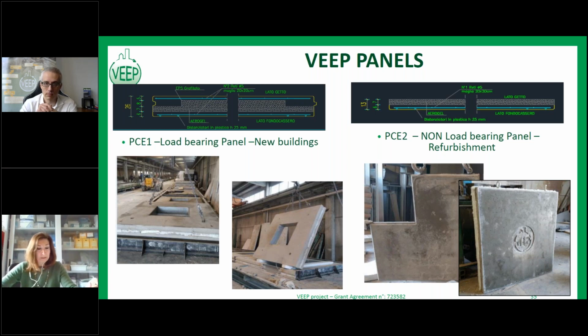This construction element, as I said, is commonly used for industrial buildings. The PCE1 concrete mix includes normal weight recycled concrete and aggregates, up to 75% of weight of replacement. The compressive strength is higher than 40 MPa, and it has 240 minutes of fire resistance. It has a lower weight per square meter and a higher U value compared to a standard construction element similar to this one. While the PCE2 is,